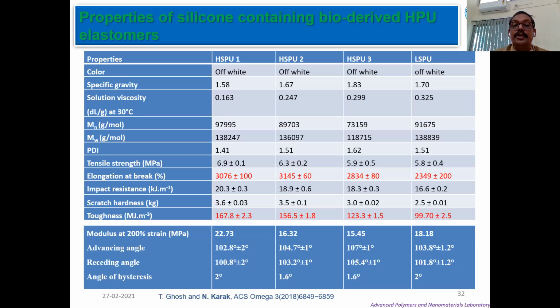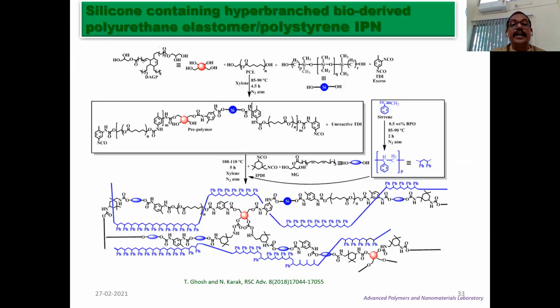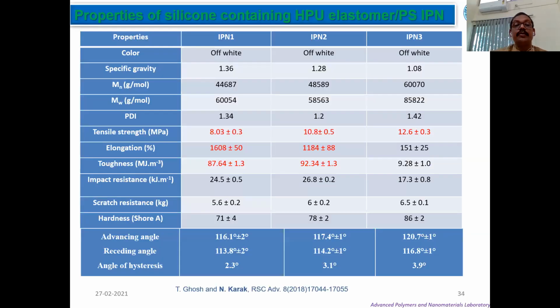We thought that because of the softness character of polydimethylsiloxane, this is happening, but we want to retain the hydrophobicity. So it is further modified by using a hydrophobic moiety like polystyrene, which is synthetic, just to see if our idea works or not. We have produced a simultaneous polymer network to get polyurethane elastomer and polystyrene network, and we have seen that by this process we are able to increase the hydrophobicity further.